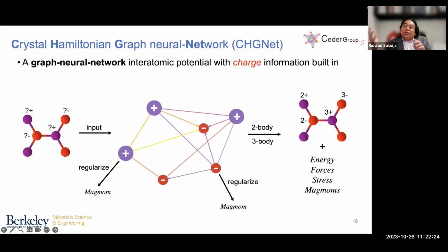The other thing I would mention is that it is already described in the paper that global charge neutrality is not included, as you alluded to. However, the error for your magnetic moment is extremely low. Yes, true. As Professor Sakidja has said, global charge neutrality is not strictly enforced under the formulation of charge inference by magnetic moments. This has been a challenging task, since you would need some spontaneous symmetry breaking within these graph neural networks to enforce strict global charge neutrality. But in application, we have seen that the predictions of CHGNet most of the time satisfy global charge neutrality, which is a good sign.